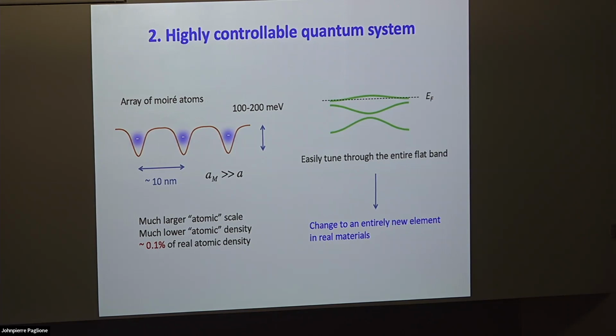The Moiré potential is actually related to the periodic modulation of the interlayer tunneling. And that periodic modulation can have a phase. If you have a phase there, you can change the Moiré potential landscape. And you can sort of think of that as a change of the atomic structure of the crystal. But you can forget about the original material. Selenium, tellurium, it's no longer important.